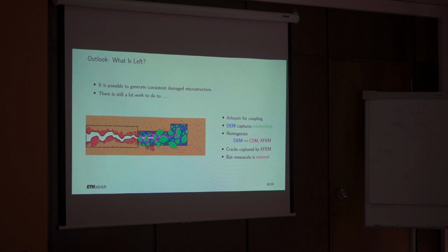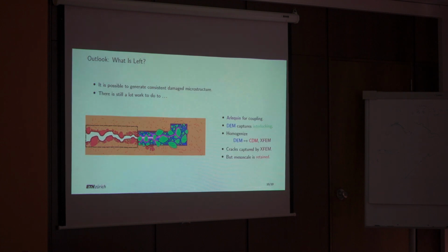However, I want also to tie this behavior in this phase to the microstructure. So I retain the surface particles, and by that I get a very sophisticated traction separation law, which tells me how the crack surfaces interact with each other, and so I can also simulate the interlocking even after I have homogenized.